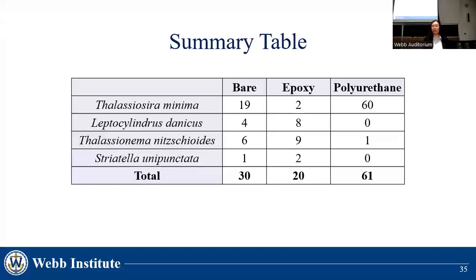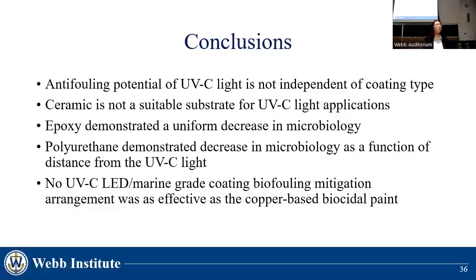Previous work has demonstrated that microbiology types may be immune to UVC light application. This may explain the high concentration of Thalassiosira minima seen on the polyurethane plates. In conclusion, it is clear that the anti-fouling potential of UVC light is not independent of coating type, and several changes in the growth were observed.